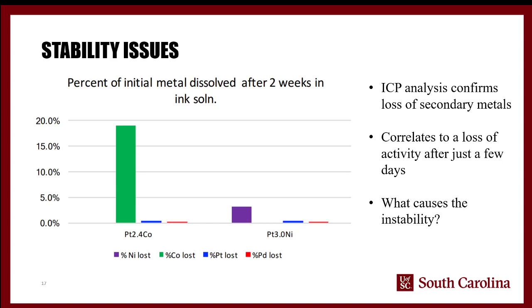And so, of course, the question was, why all of a sudden do we see this massive decrease in activity? And as it turns out, when we did ICP analysis of the solutions, there was a whole lot of cobalt and less, but still not an insignificant amount of nickel sitting in solution. And so what that means is that the catalyst was leaching out, or the cobalt and nickel were leaching out into this water IPA solution. And it turns out that it actually happens after just a few days.